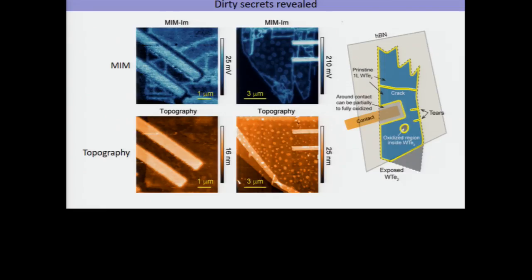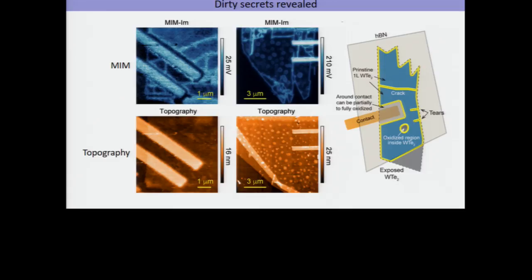We think this happens because of tenting. When you put the WTe2 down over the edge of the platinum contact, it wraps down like that. It goes down trying to conform, but it doesn't manage. And there's a little channel there, and air or water or something can get in there and cause the material, whoops. I wish this worked. I just paid $40 for this.